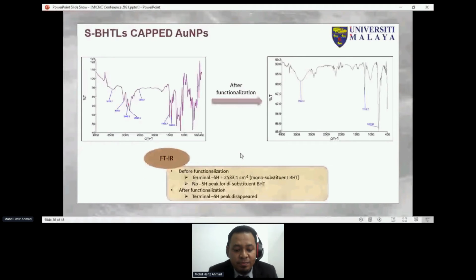For the FTIR spectrum, it showed the attachment of ligands on the gold surface. Before functionalization, the terminal thiols of the mono-substituent BHT appear at this peak, then disappear after functionalization. But the disubstituent BHT ligands have no thiol peak because they don't have a terminal thiol at the end of the ligand. In this case, the confirmation of functionalization for disubstituent BHT ligands is supported with EDX data and biological activities. So, all data in this part show that the functionalization of ligands on the surface of gold nanoparticles was successful.